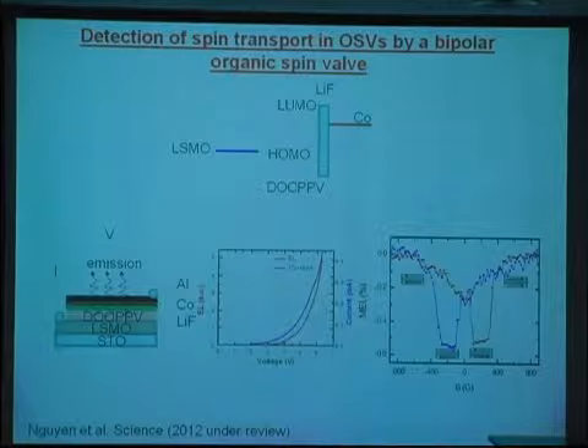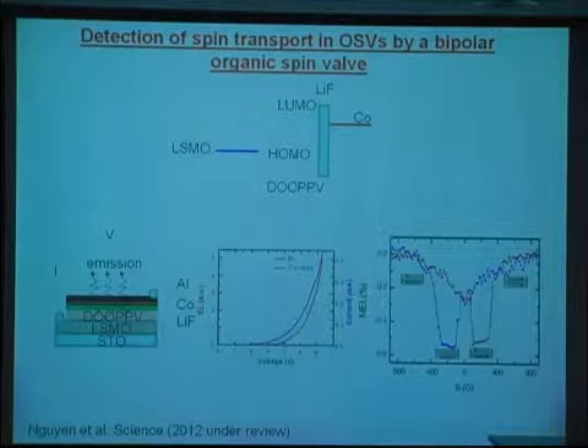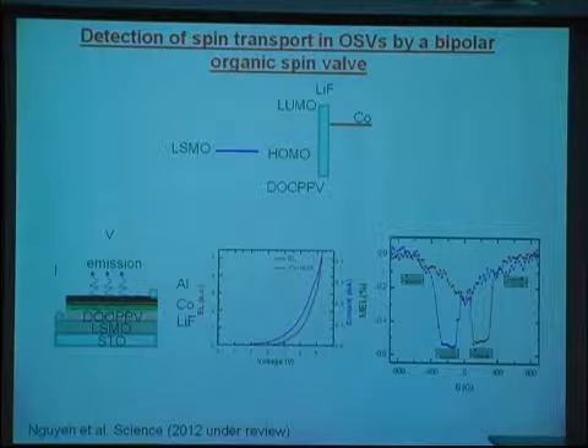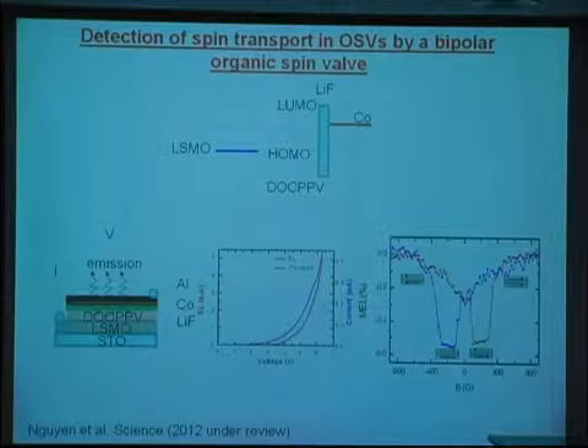Okay. And I think that because the spin diffusion length is too small, if you want to make the horizontal organic spin valves, the 2 electrodes need to be about 50 nanometers apart. This could be very tough. If you make it too far, 2 electrodes cannot talk to each other. Why can't you take vertical structures? I don't know, and I am not aware of any study, even in the inorganic community, where people study the Hanle effect in the vertical. There's some reason, but I don't know yet.